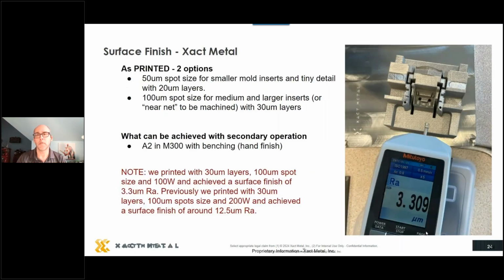So what we've done here, as I mentioned, is that our machine can be adjusted, tailored or fine-tuned. We've printed this insert you see on the top right. Again, that's that 3x3 insert I mentioned earlier where we held 2 thou tolerance over the whole thing. The initial print at 200 watts with 30 micron layers, I don't want to get too far down in the weeds here, but it all makes sense. When that part was printed, we had about a 12.5 micron Ra surface finish on it, which was a bit too rough.